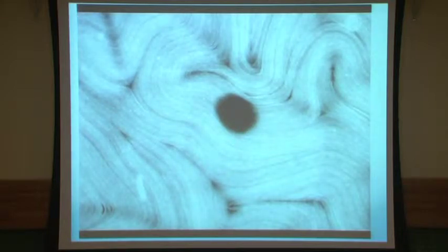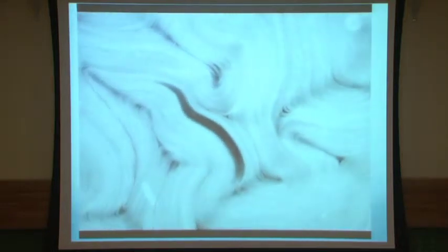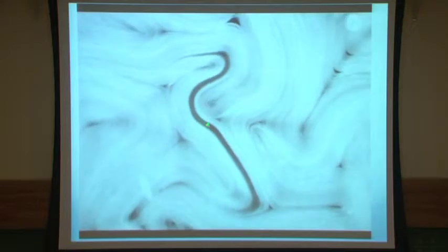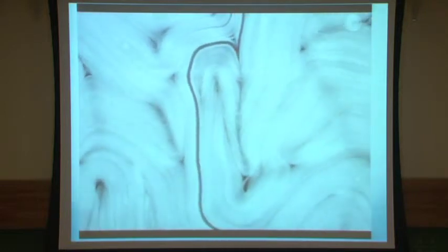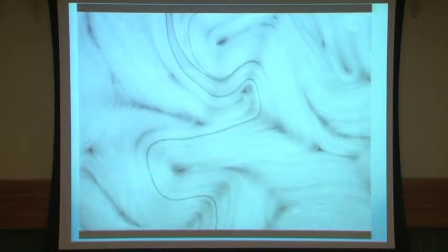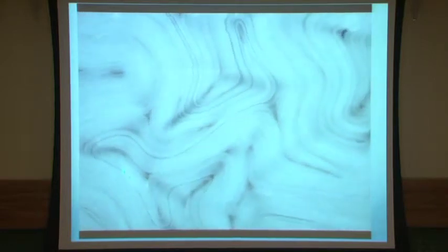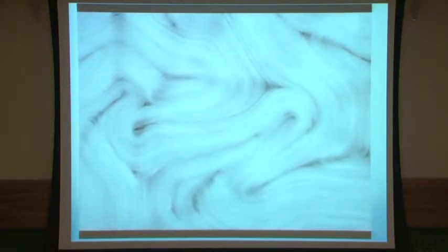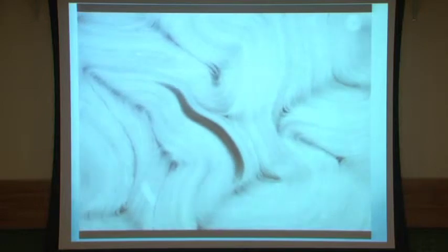You bleach a spot, and then you let your active nematics run, and you nicely see the extensile nature of these microtubules. They're essentially becoming longer and longer, and you can see this drop becomes thinner and thinner until you can no longer see it, right? So this is really like kneading a dough, right? As you stretch, and then you fold, and then you stretch, and then you fold.